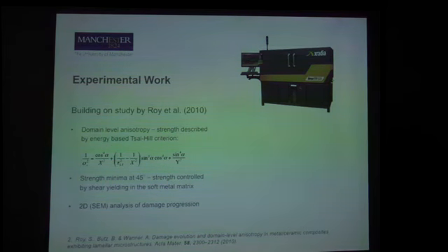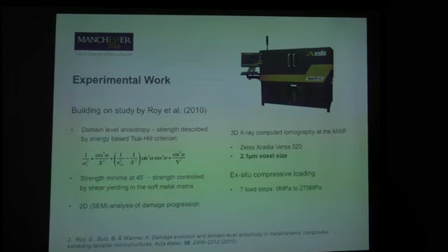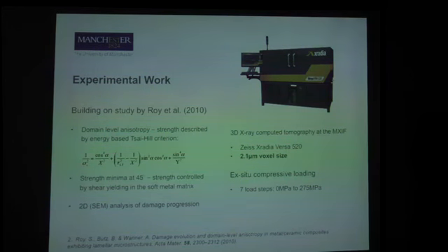Part of what I want to do is build on this, because is 2D really sufficient when you've got this complex crack development? Do you perhaps need to look in 3 dimensions? That's precisely what we're starting to do, using some of the facilities at the Henry Moseley Manchester X-ray imaging facility. With this X-Radia Versa 520, we've got a voxel size of about 2 microns for the volumes we're producing, and we're doing an ex situ series of compressive loading steps from 0 to